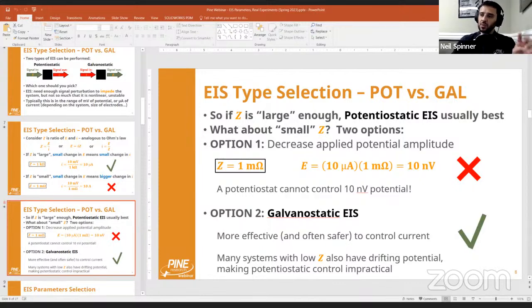With galvanostatic, unless you're doing a set current, like you're adding a milliamp and then doing a sine wave on top of it, which is rare, most of the time galvanostatic is just at zero current, and then you add your impedance. That means that it's always at OCP. It's necessarily riding on OCP. So what's not implied or understood sometimes about potentiostatic impedance when you do it at OCP is you're not at OCP. You're in potentiostatic mode.